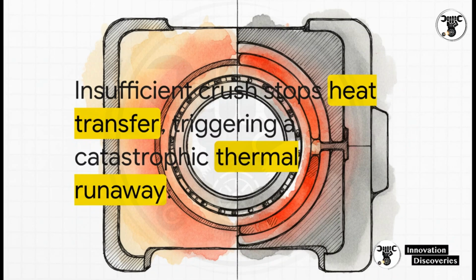Bearing shells are intentionally manufactured just slightly larger than the circular bore they sit in. When you torque the connecting rod cap down, it forces an interference fit. This isn't just to keep the bearing from spinning. This crush-generated contact pressure is a non-negotiable mechanical necessity that conducts heat away from the bearing and dumps it safely into the engine block. Insufficient crush ruins that thermal contact. The bearing gets hotter, the oil film boils and breaks down, and boom, you trigger a catastrophic thermal runaway.